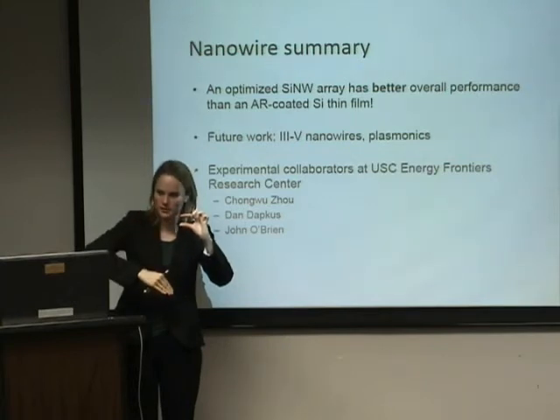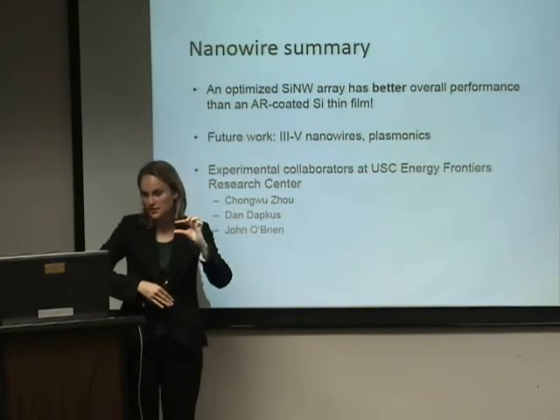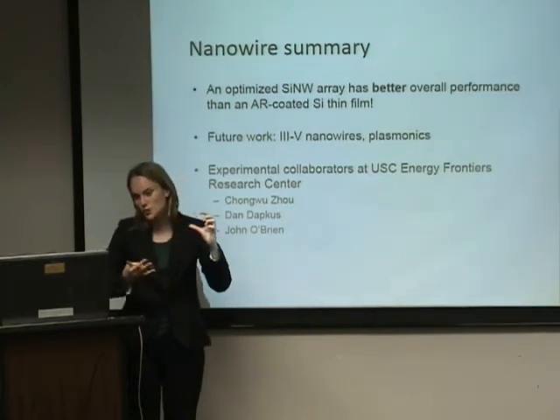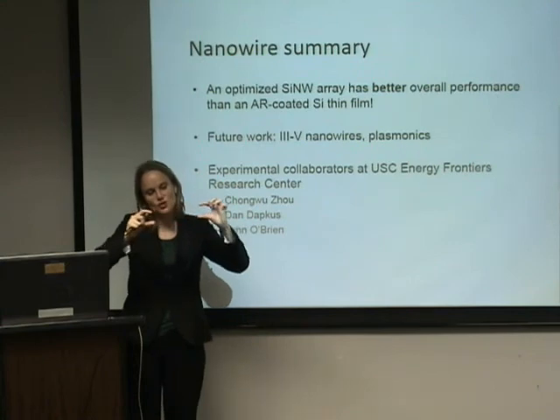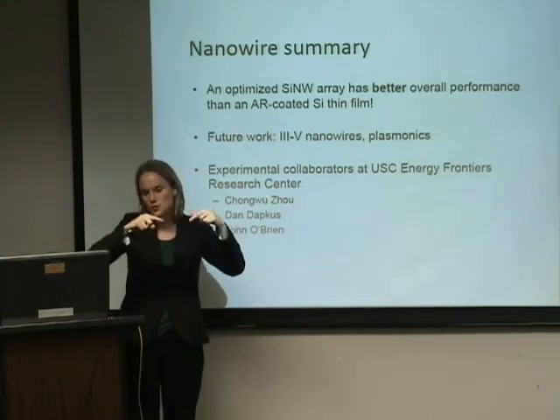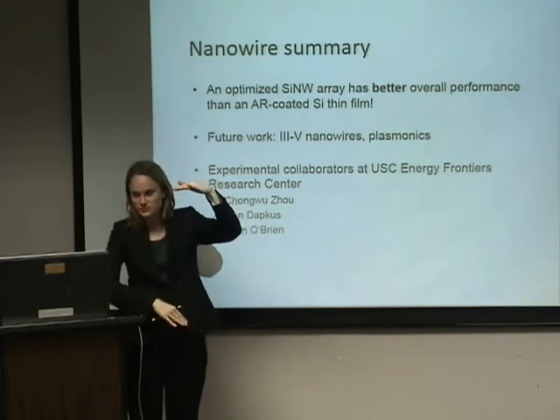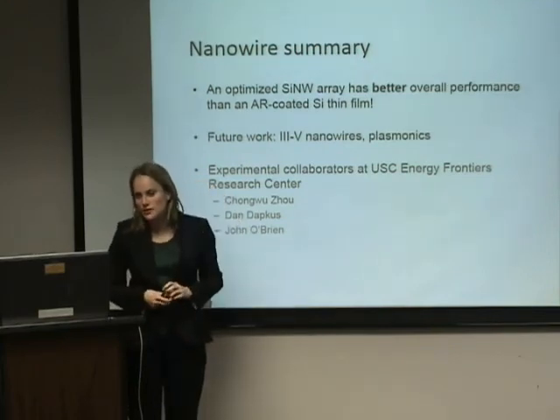It would actually take a longer length to absorb a reasonable fraction of the light in the range where you have low absorption. So this structure is kind of a way of getting more absorption within a short thickness. If you went really long, you wouldn't necessarily need that.